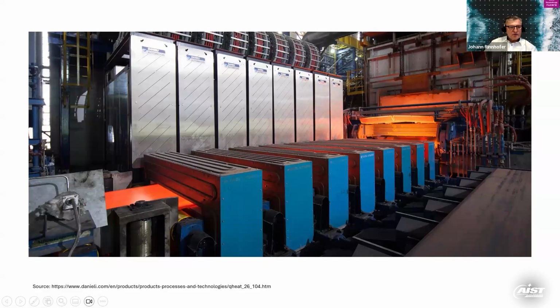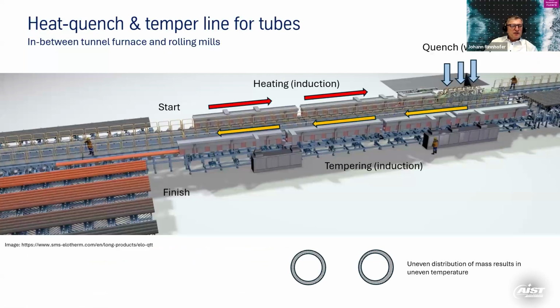What you need. So heat, quench and temper lines for tubes, a very interesting concept. So you start with a cold tube, for example, for drilling tubes or something like that, oil field tubes, go into induction coils, heat it up to 1000 degrees approximately, go into a quench with water, come back again, go into the tempering furnaces for the tempering, and also with induction coils,